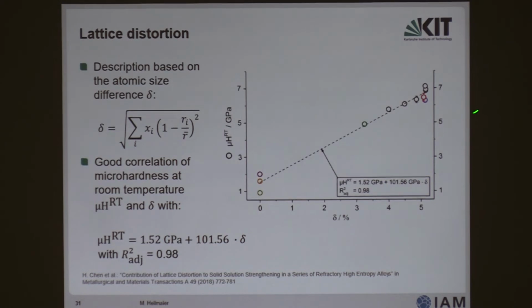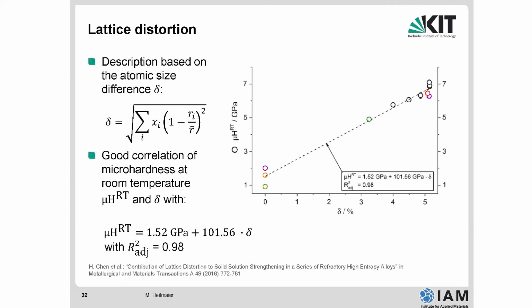Okay, and of course, with this, we can describe the increase of hardness, taken at room temperature in this case. Here you see the hardness of the pure elements. They are very soft. But then once you make these various alloys, and each data point again corresponds to one alloy, the hardness increases quite a bit. And this tells you that the lattice size mismatch, or the atomic size difference, scales linearly with the hardness increase. This is the important take-home message here.